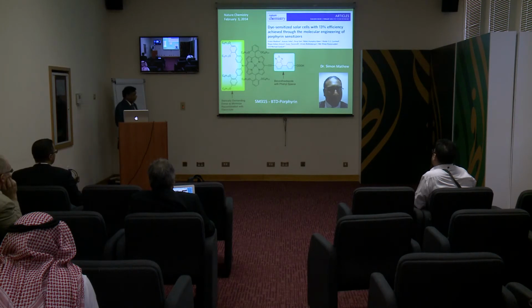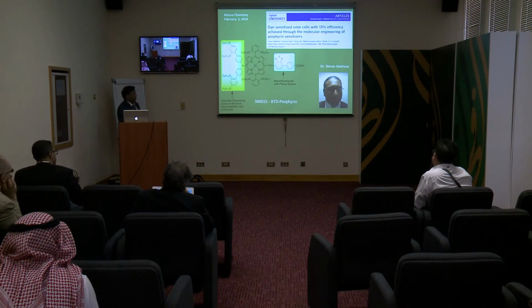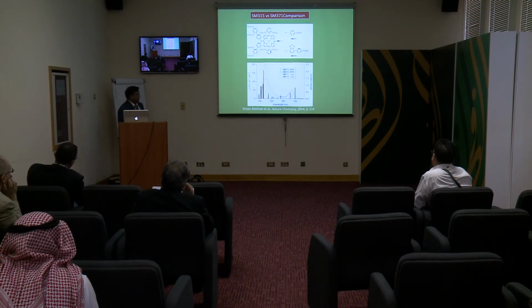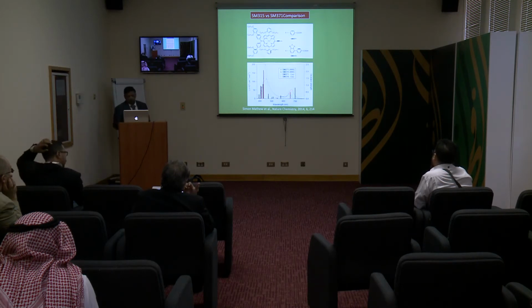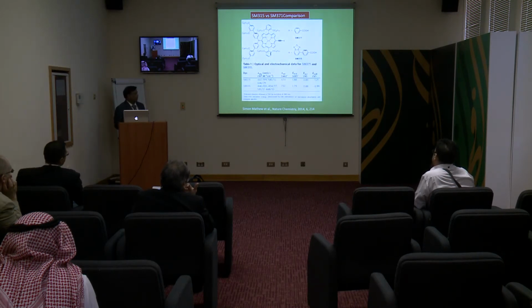And now we are putting together the organic dye with the porphyrins, introducing the benzothiadiazole there, which also adds to the performance we have seen with organic dyes. For example, here you can see the broadness of the spectral shift and the shift in the absorption spectra. It contributed to higher performance, reaching up to 13% with this one.